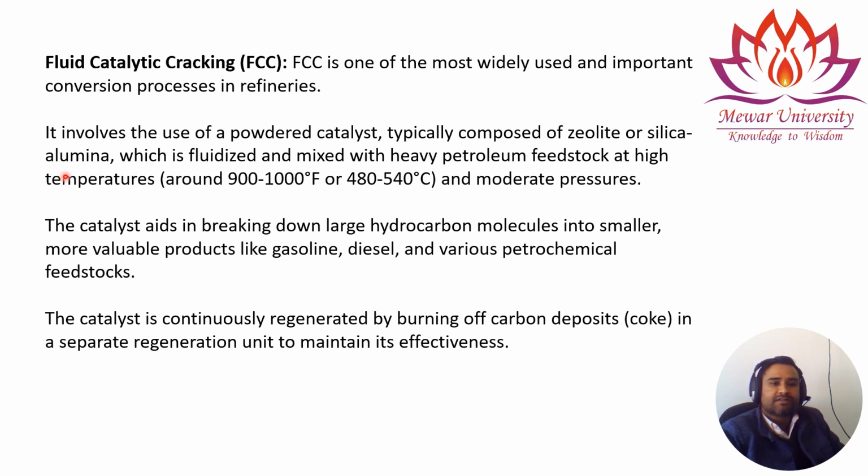This is another important catalyst used in the FCC unit, which is fluidized and mixed with the heavy petroleum feedstock, that is heavy hydrocarbon, at high temperature. The temperature is around 900 to 1000 degrees Fahrenheit, or 480 to 540 degrees centigrade, at moderate pressure. The catalyst aids in breaking down the large hydrocarbon molecules into smaller, more valuable products like gasoline, diesel and various petrochemical feedstocks. The catalyst is continuously regenerated by burning the carbon deposit, coke, in a separate regeneration unit to maintain its effectiveness.